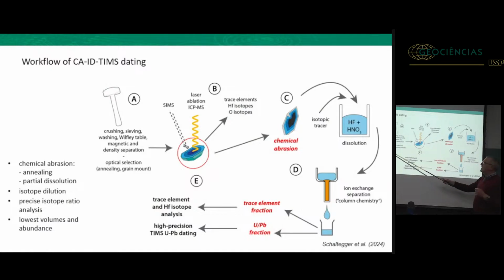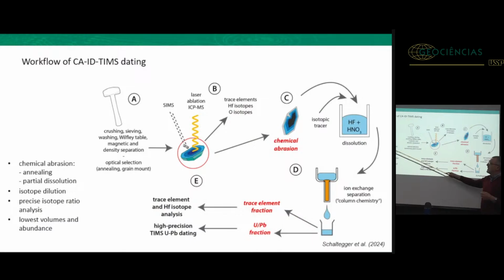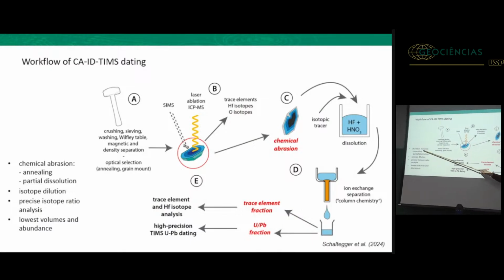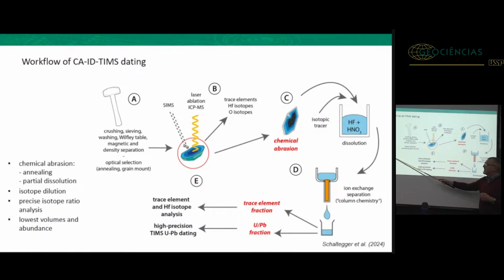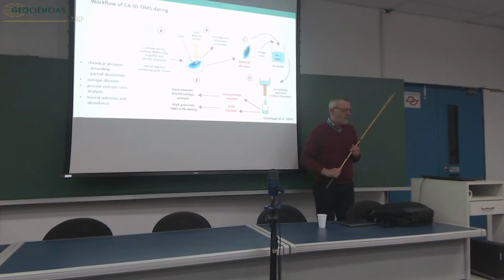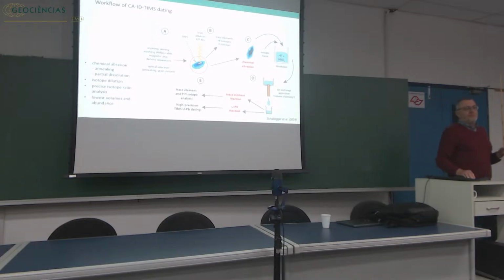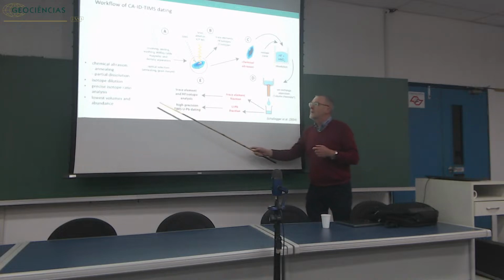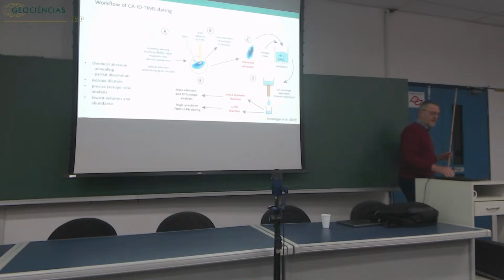So important points is that this step of chemical abrasion, which I will get back to, consists of two steps. We will see this annealing at high temperatures and then partial dissolution. And the other important point is that there is a step which is called isotope dilution. We add a tracer. We know very well the concentration and isotopic composition of this. We have a precise isotope ratio analysis, which is TIMS, thermal ionization mass spectrometry. And we can deal with lowest volumes and lowest abundances. So we can measure a picogram of lead at the precision of per mils or better in lead isotope ratio.